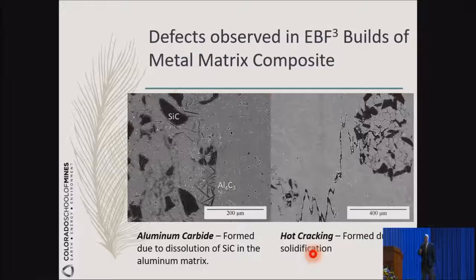Okay? So there are some problems, some defects that go with it as well, is that if you put silicon carbide into aluminum alloy, the silicon carbide going through that arc source or going through the electron beam source or laser source, they will decompose, and the carbon will be picked up by aluminum as Al4C3. And those are bad for the mechanical properties, crack opening, and so on. In this case here, you see on the left-hand side here, silicon carbide dispersed in aluminum. On the other hand, on the aluminum side, you also run the possibility of hot cracking as well.